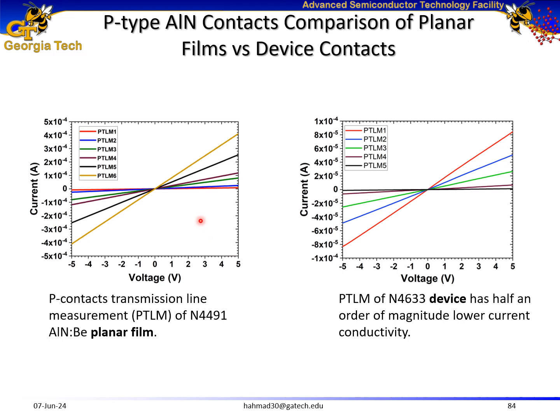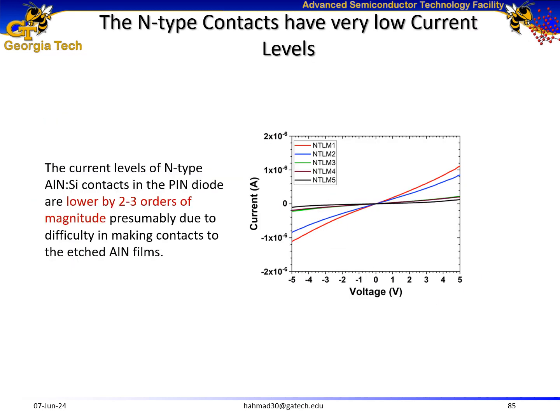From PTLM comparison of a planar P-type film versus the PTLM on the device, we see that our current conductivity was slightly lower as compared to the planar film, but they were still comparable. However, for the N-type aluminum nitride device contact, our current conductivity was 2 to 3 orders of magnitude lower as compared to the planar film. We suspect that this is due to the damage introduced during the etching process. I repeated this study, but once again I encountered the same issue, and this is something which requires improvement in the future.